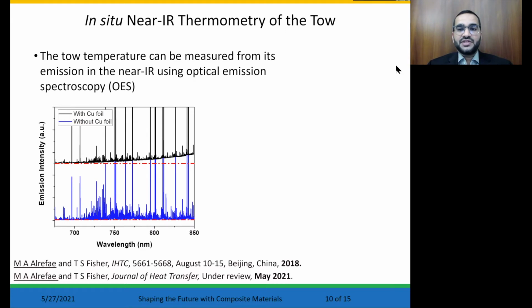The numerical model was benchmarked with the analytical model as reported in our previous work. The temperature distribution was validated with in situ temperature measurements, which were measured with optical emission spectroscopy. For example, the emission spectrum was measured in the substrate vicinity with and without copper foil in our previous work. When copper substrate was not included in the plasma, the baseline remains flat with emission from plasma species. However, the spectrum, when copper foil was included, has an increased baseline, which corresponds to the emission from copper surface and contribution also from plasma species. The baseline can be fitted with Planck's distribution to infer the substrate temperature during the roll-to-roll process.